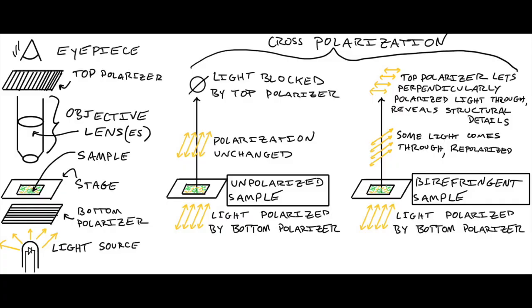You can do quite a lot with optical microscopy, particularly under polarization or dark field imaging. Polarization microscopy is where you use polarized light to shine through a sample. If that sample has polarized elements in it, say anisotropically stretched structures, then that will shine through more brightly than cross-polarized regions. You can also use two polarizers oriented above and below the specimen so that you can see how much that specimen will rotate the light, which is useful in detecting spherulites in a polymer sample, which appear as a Maltese cross-type structure, which is pretty cool.